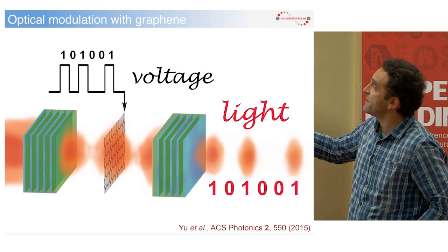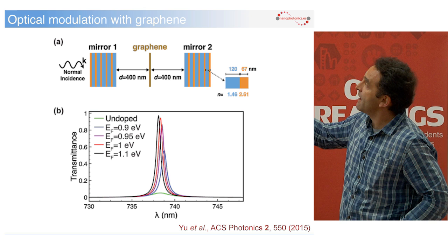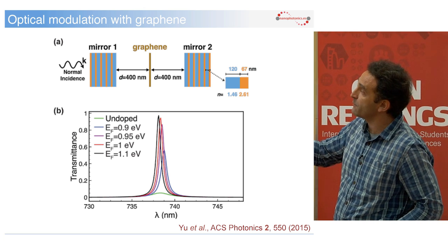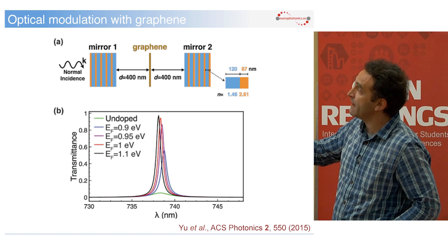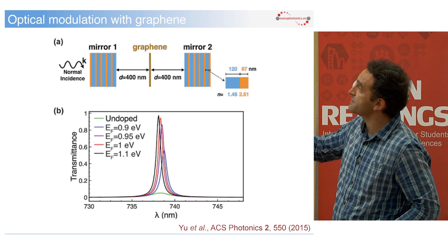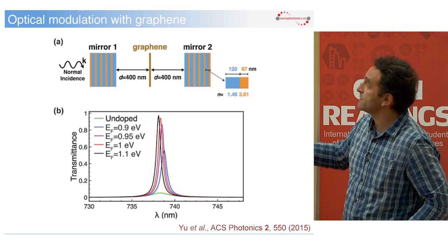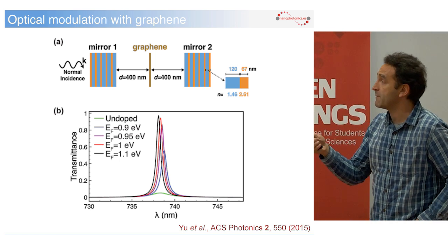The plasmons live in the region that is precisely staying in this gap between interband and intraband transitions. You can see, for example, with a certain doping, then you have an optical gap. Vertical transitions have a gap that is twice the Fermi energy. So this is the gap. And eventually it closes down when you consider oblique transitions, right? That's where the plasmon is, okay?